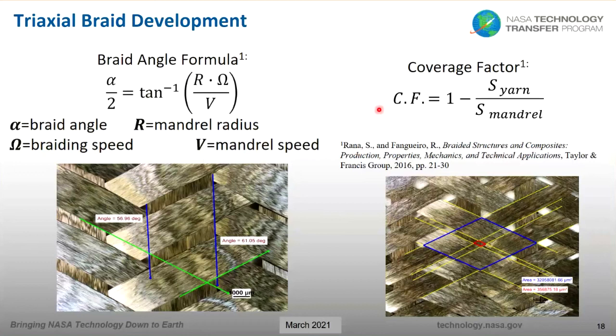So this equation takes into account the surface area of the braiding yarns and the surface area of the mandrel. And in the image on the bottom right, I intentionally show the change in coverage factors from a low coverage factor where you have these open spaces to a higher coverage factor at the bottom of the same micrograph, where there's hardly any open spaces. But your application will determine the best braid angle and coverage factor that you should use.